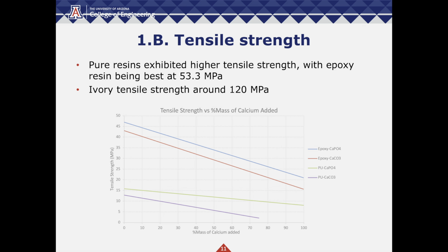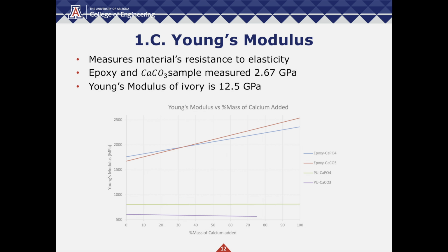Our data for the test showed that pure resin samples have a higher tensile strength, and adding calcium makes it weaker. Our best sample was pure epoxy resin, which produced a tensile strength of 53.3 megapascals, while ivory has a tensile strength of around 120 megapascals. Data on Young's modulus was also collected with the tensile test.